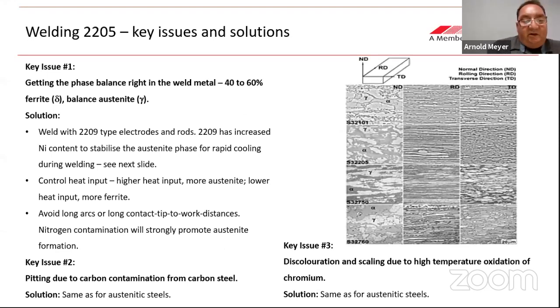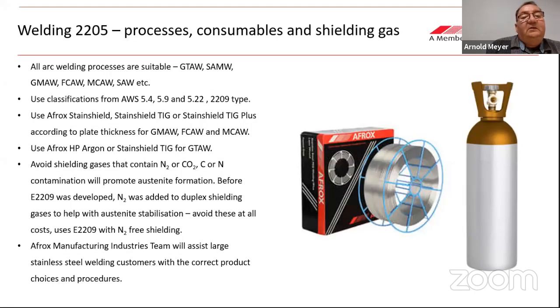The other key issues are exactly the same as for austenitic stainless steels. I'm not going to repeat it here. Then also for duplexes, you can use all the processes, classifications from 5.4, 5.9, and 5.22. For 2205, always use 2209. For these, you want to avoid shielding gases with nitrogen or CO2 in them, because carbon or nitrogen contamination will promote austenite formation. Here you want to look at normal Afrox stain shield TIG for all processes, or TIG plus